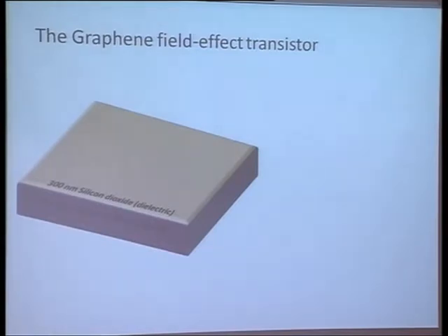Most graphene-based devices are made on an insulating substrate, which has a large metal underneath, which acts as a gate. So if you see, this is a silicon-silicon oxide wafer. There's a thick silicon oxide, about 300 nanometers. Below that, there is heavily doped silicon, which is metallic. So you can apply a voltage on that to make a gate.